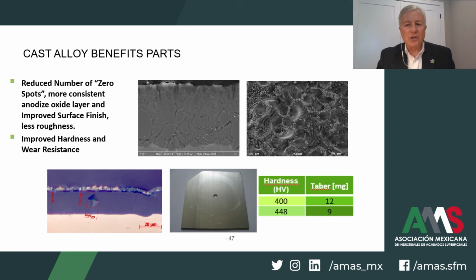With a complex geometry part shape, there are low areas of anodic oxide thickness, commonly referred to as zero spots. The part performance is then degraded. With the proper thickness range, the oxide has good surface profilometry, and that will exhibit a smoother, brighter anodic oxide surface, and that will demonstrate improvements to the oxide hardness and the corresponding wear resistance. These are all the factors that equate to an improved part, a component that is processed through stage 1 and stage 2.